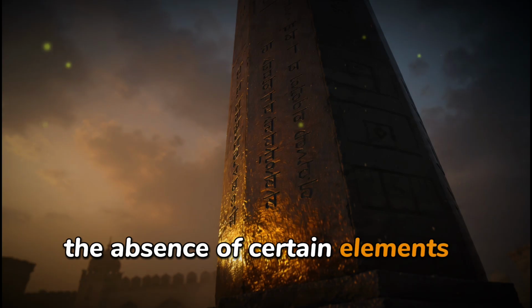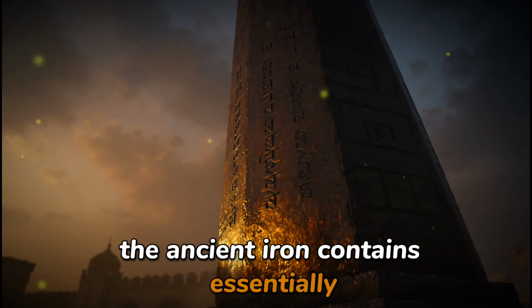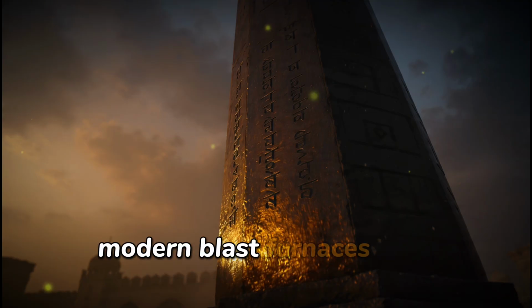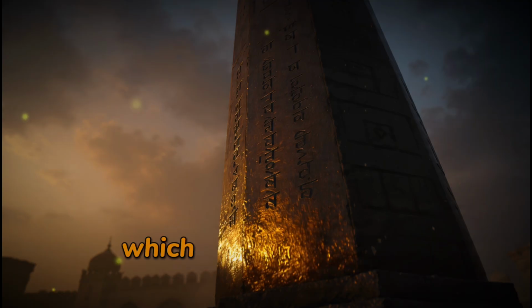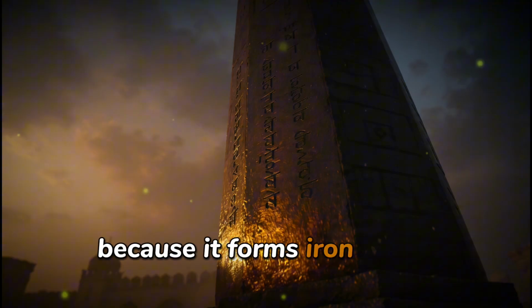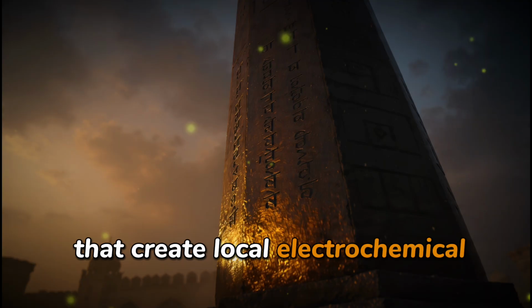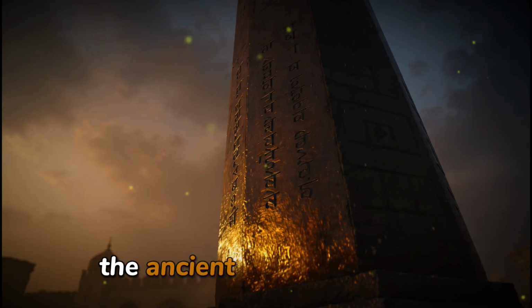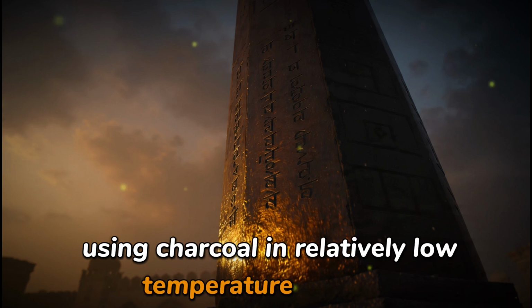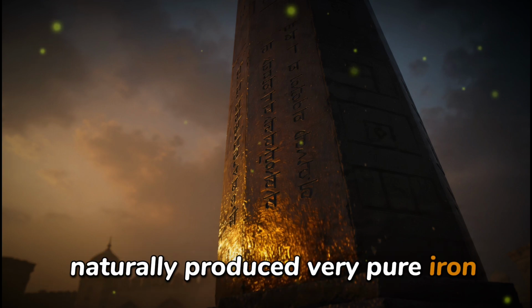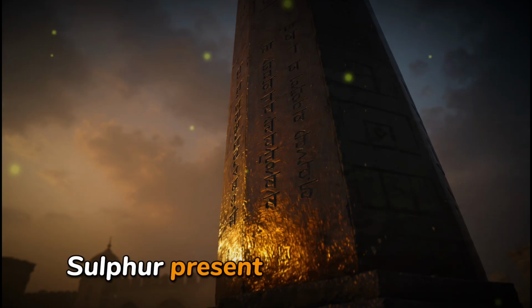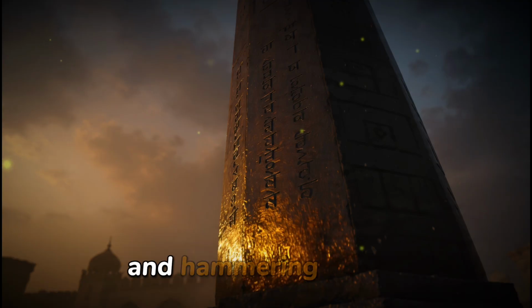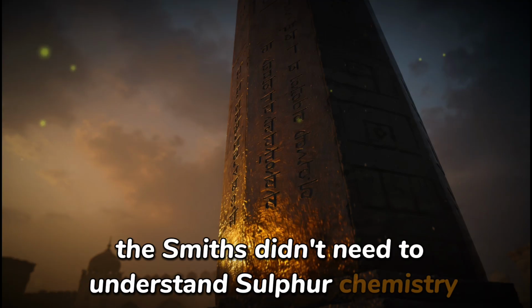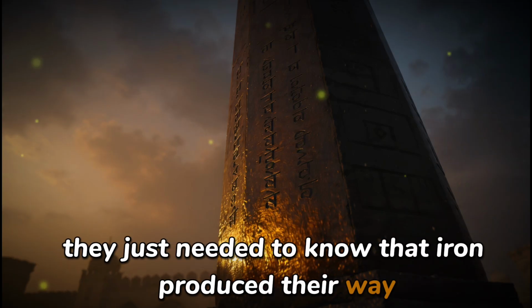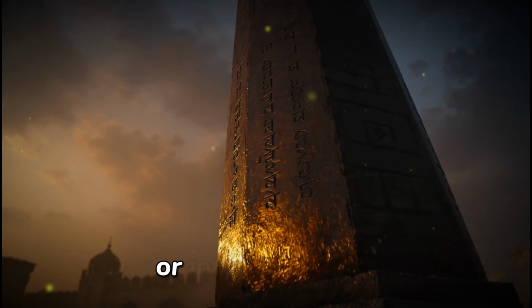The absence of certain elements is also crucial. The ancient iron contains essentially no sulfur or phosphorus. Modern blast furnaces often introduce trace amounts of these elements, which can interfere with protective film formation. Sulfur, in particular, can cause problems because it forms iron sulfide inclusions that create local electrochemical cells, accelerating corrosion. The ancient smelting process, using charcoal in relatively low-temperature furnaces, naturally produced very pure iron with minimal contamination. Sulfur, present in many iron ores, gets removed during the prolonged heating and hammering process. The smiths didn't need to understand sulfur chemistry. They just needed to know that iron produced their way lasted longer than iron produced by shortcuts or inferior methods.